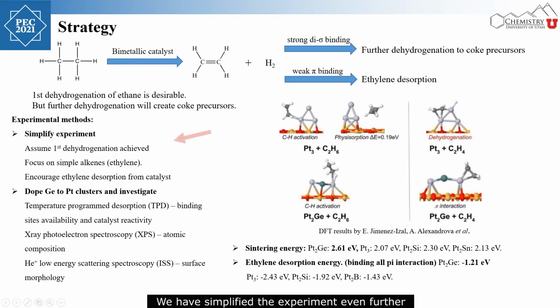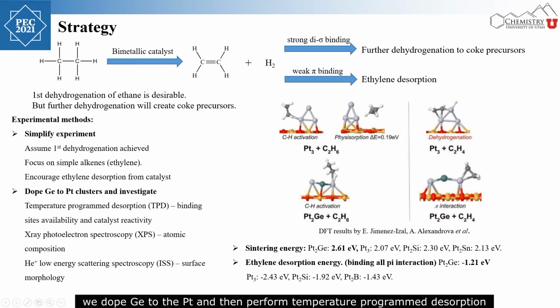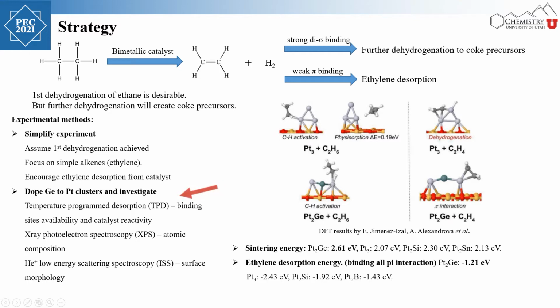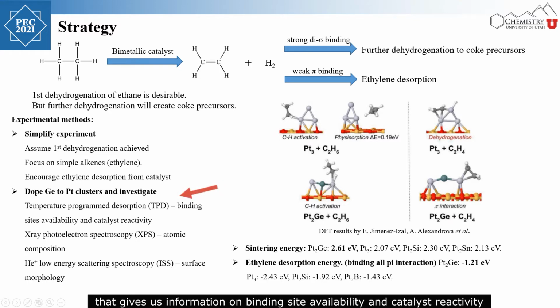We have simplified the experiment even further by assuming that the first dehydrogenation is easily achievable and only focus on whether ethylene dehydrogenates or desorbs from different catalysts after the first dehydrogenation. For analysis of catalyst properties, we dope germanium to the platinum and then perform temperature-programmed desorption that gives us information on binding site availability and catalyst reactivity.